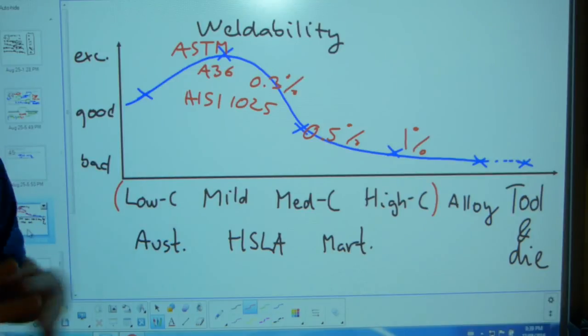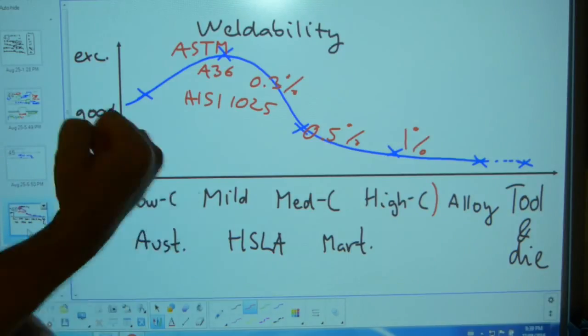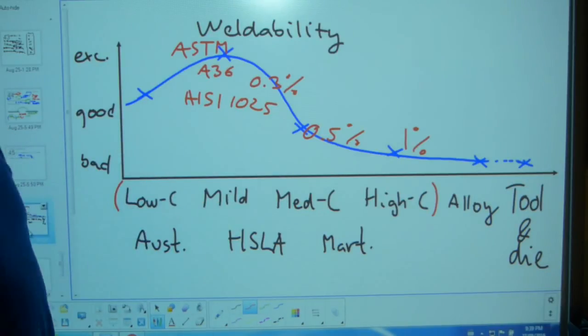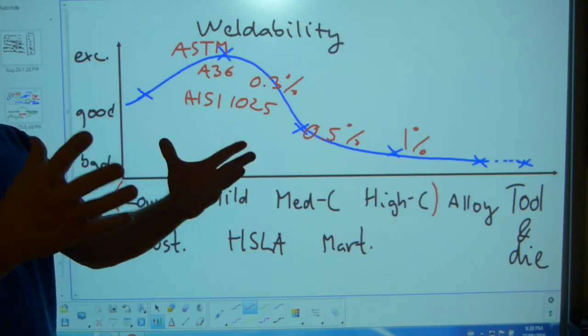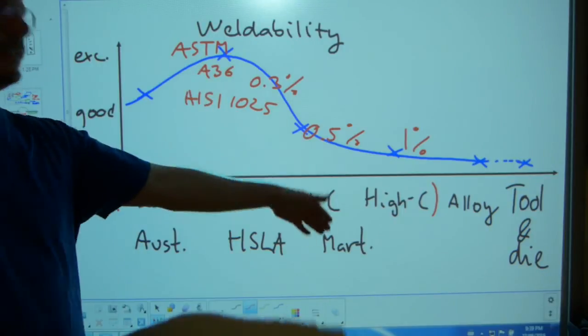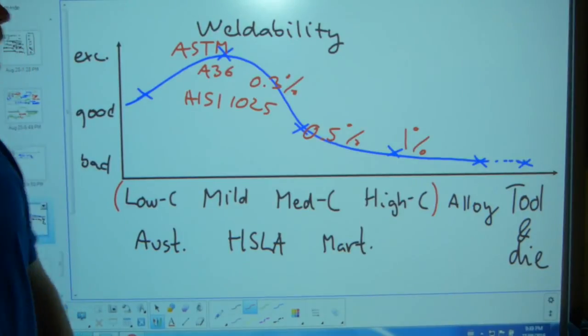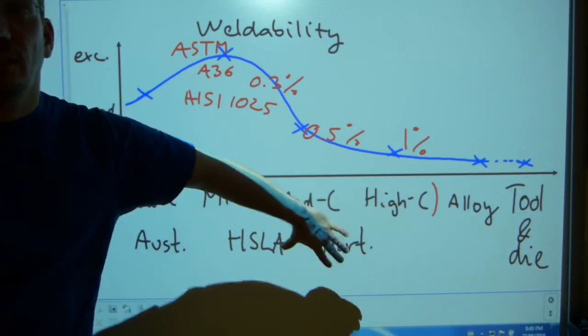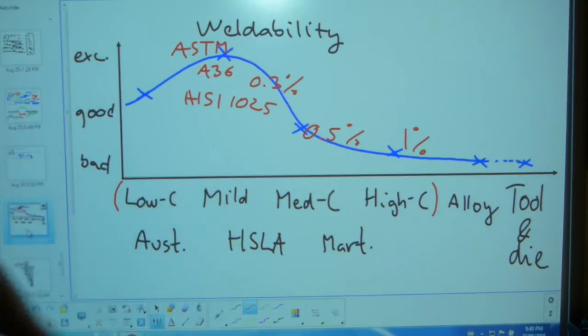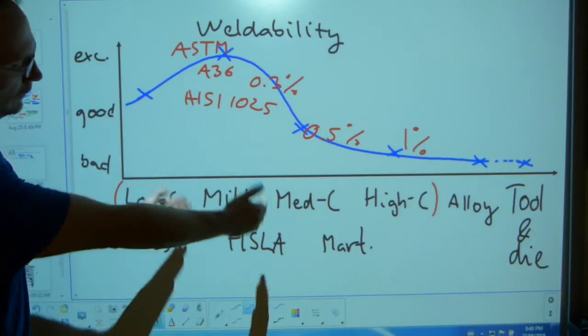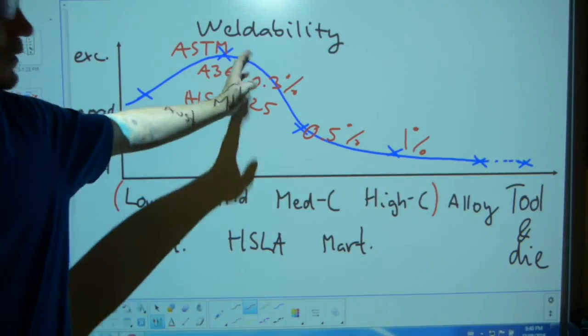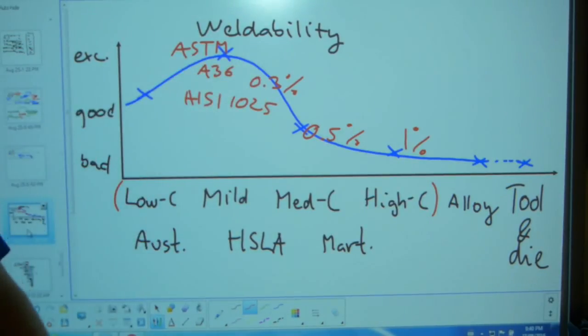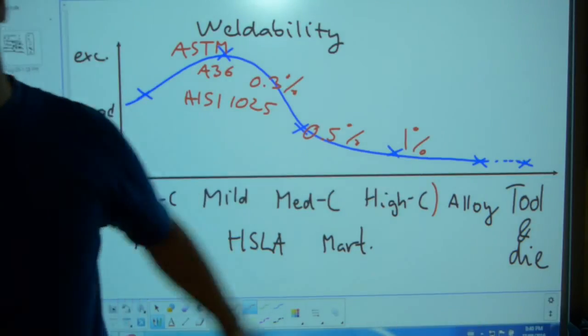Just like welding back a claw of a hammer doesn't work, because it holds only for one pull, and then the claw breaks off again due to the high carbon content and graphitization of the originally dissolved and evenly distributed carbon. So nobody welds a chef knife together or a claw hammer back. So that's why martensitic steels are kinda here and kinda here. Some of them are better weldable. Automotive mufflers are super weldable. Alright. High strength low alloy steels are here because they have a low carbon content, they also have a low alloy content, and they are here a little past the fantastically easily weldable, going into the downhill range where they are weldable with caution. But most other alloy steels, besides the low alloy, they are there for this reason.